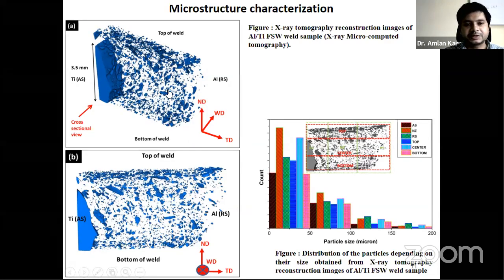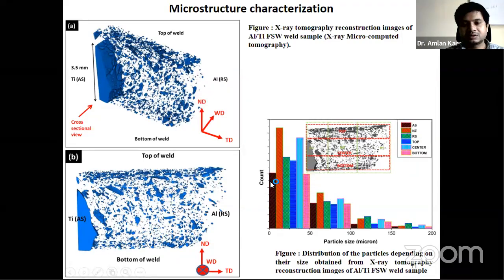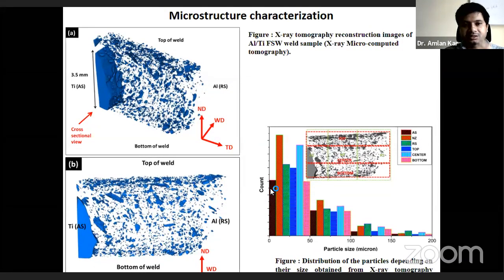Even in the original image, you cannot get a better understanding of how the deformation took place and what kind of distribution has taken place. But one thing you can understand is that throughout the weld nugget, you have some particles. So the particles are more or less homogeneously distributed, or you can see that in all locations you have some particles.